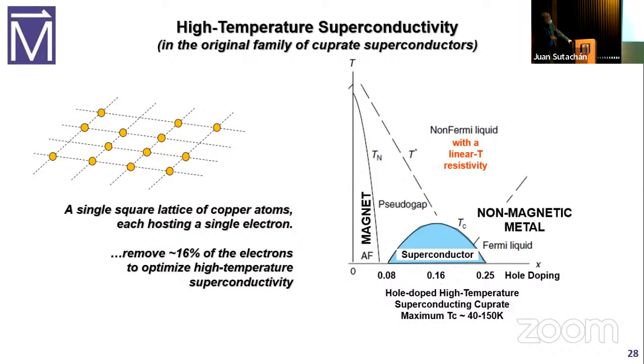Well, all of the materials of this particular family, called the cuprates because they have copper, have a square lattice of copper atoms. Everywhere these lines intersect, there's a copper atom. And then you put one electron on most of them, but you remove about 16% of the electrons, and you get superconductivity. So if you have an electron everywhere, it's a magnet. If you remove too many electrons, it's non-magnetic and it's just an ordinary metal. But somewhere between about 8% and 25%, for some reason, the sample is superconducting.